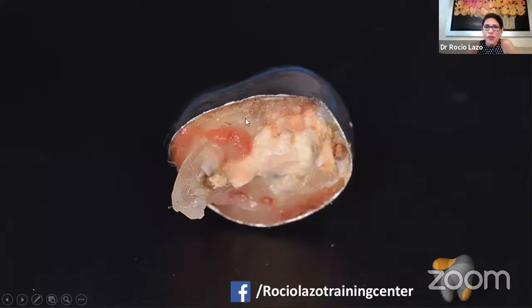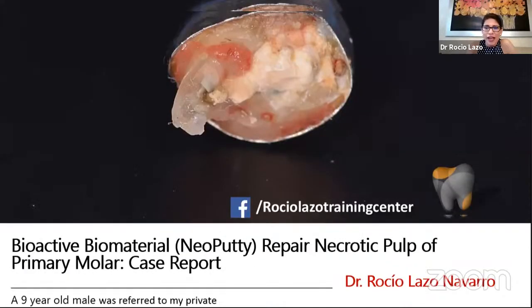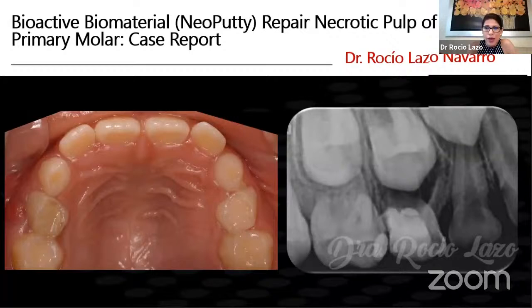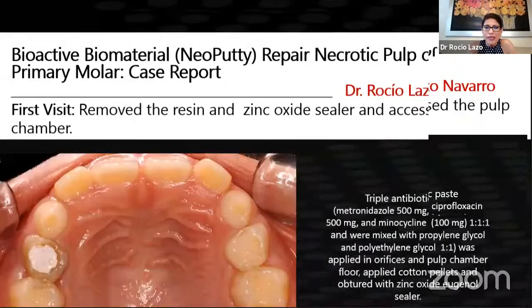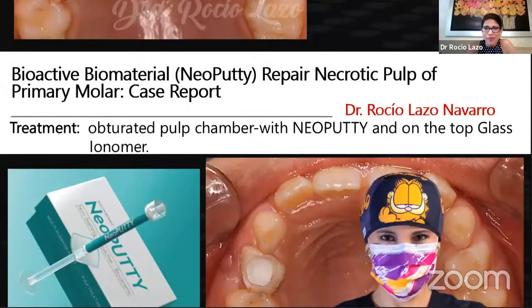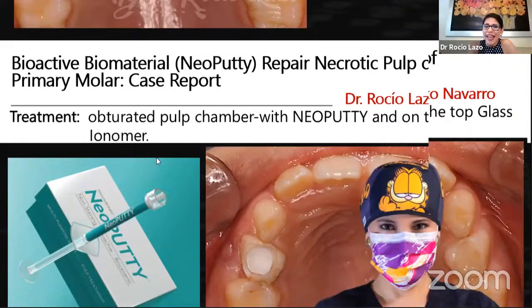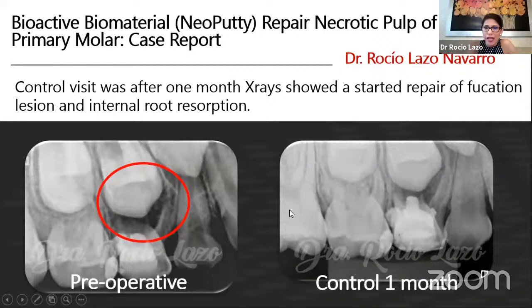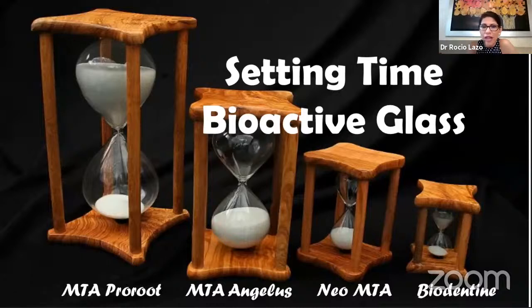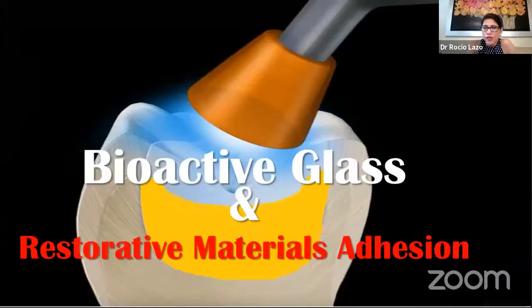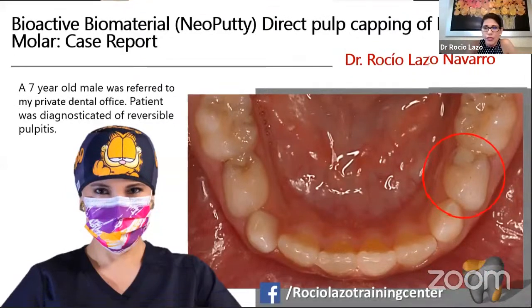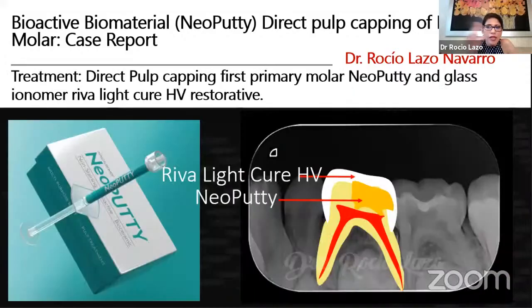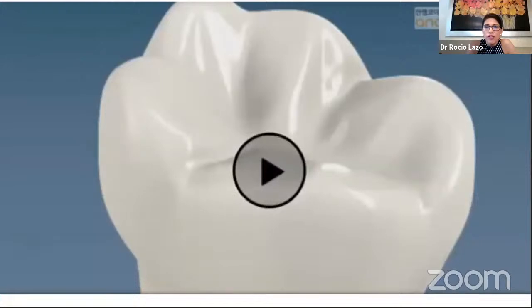So let's check. This is another case that has necrosis. I used the bioactive glass. In this case it was NeoPutty, that is pre-mixed. And let's check the x-rays. This is the preoperative, and 1 month to check the regeneration, okay? You have good results. But the problem with this bioactive glass is the setting time, and it's not a permanent restorative. So this is the problem. You need to apply on top a restorative material that will be maybe glass ionomer or maybe a resin.